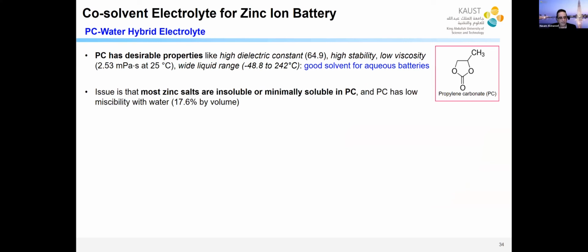So I think this study fits in the category of co-solvent. Propylene carbonate is one solvent. If you look at it by itself, it's a nearly ideal solvent for batteries. It has a high dielectric constant, which means it can make the salts dissolve very quickly. It has high stability. It also has low viscosity, which means the ionic mobility is high, and it remains liquid over a wide range, from -48 to 242 C. So if you just look at it, this is really a very nice solvent.